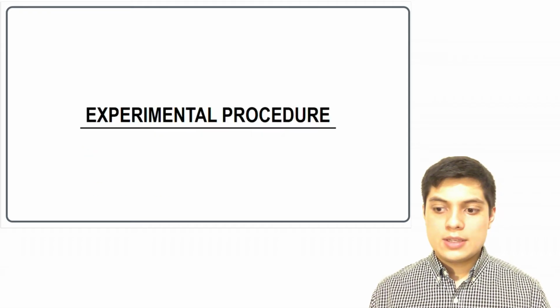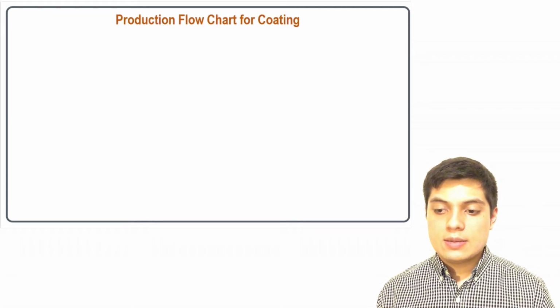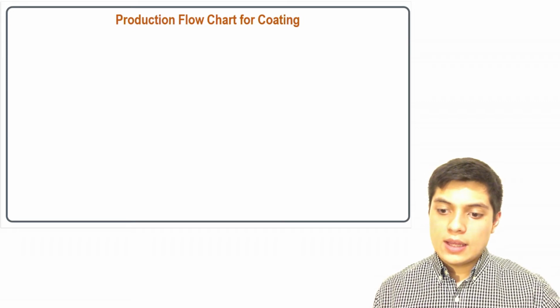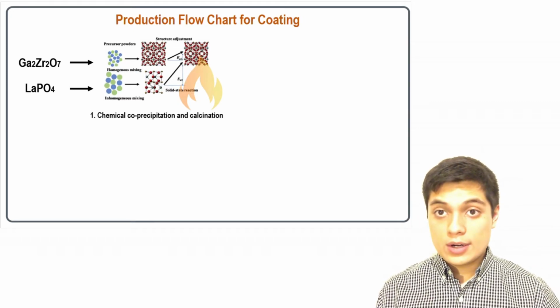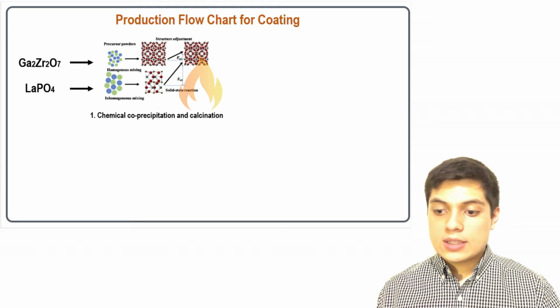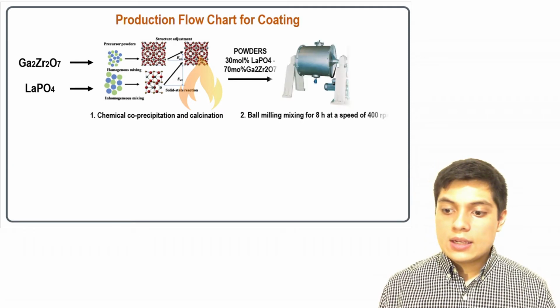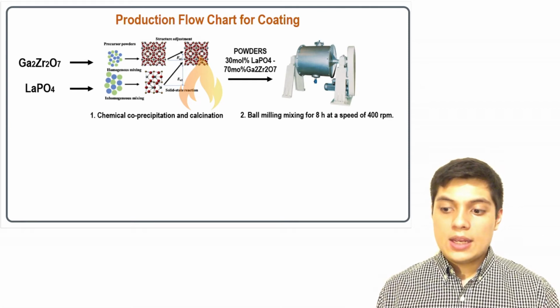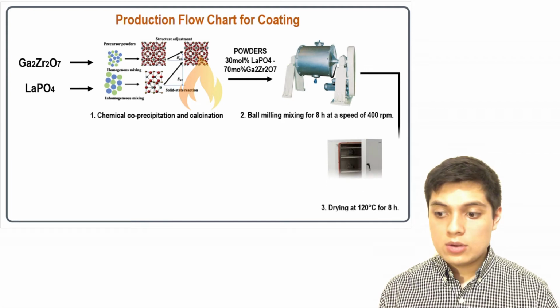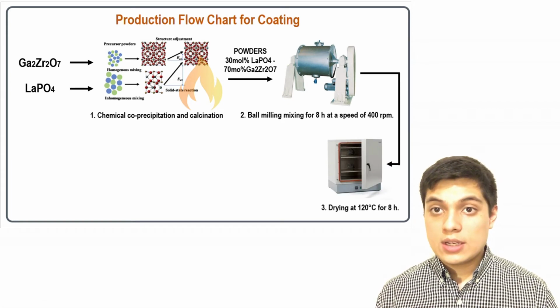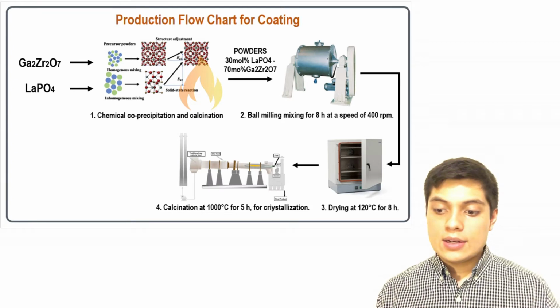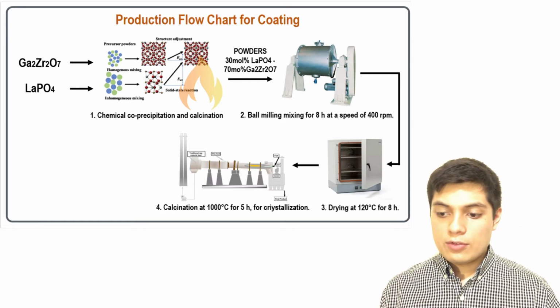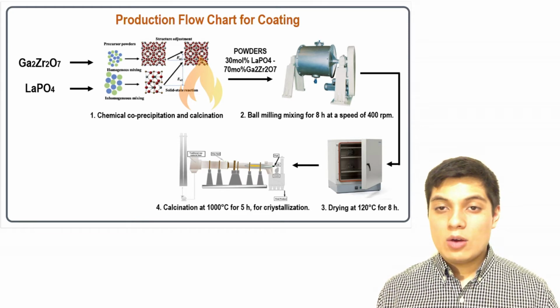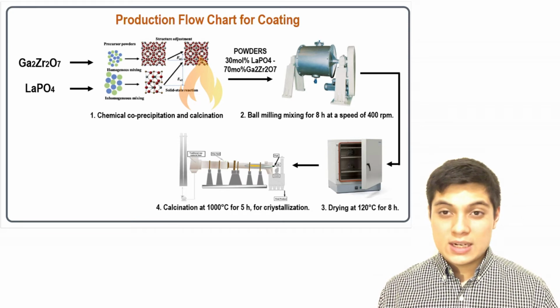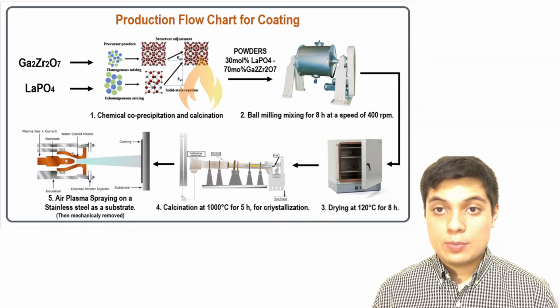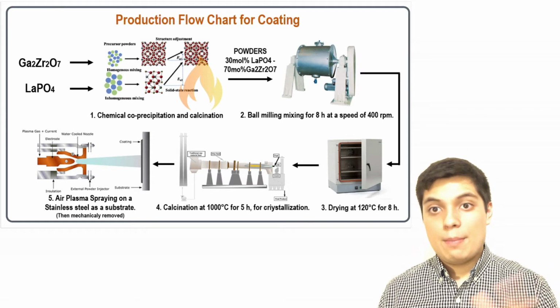So now we're going to examine the experimental procedure. And first of all, here is the production flowchart for the coating. So first, the gadolinium zirconium oxide and the lanthanum phosphate were prepared with a process known as chemical co-precipitation and calcination. Then they were mixed in ball milling for 8 hours at a speed of 400 revolutions per minute. Then they were dried at 120 degrees Celsius for 8 hours. Then they were calcinated at 1000 degrees for 5 hours, and this was mainly for obtaining a crystalline structure. And finally, the coating was mechanically removed, so experiments could be conducted in a better way.